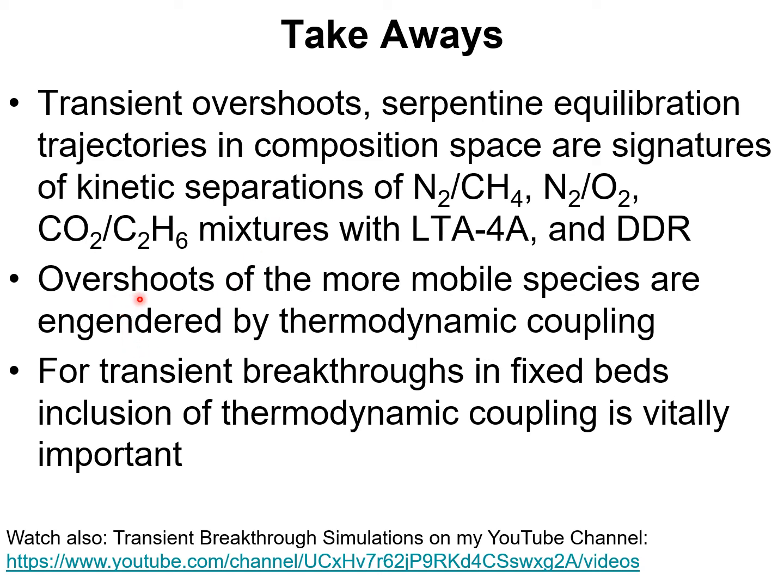The transient overshoot of the more mobile species is engendered by thermodynamic coupling effects that are described by a two-dimensional matrix of thermodynamic correction factors. For transient breakthroughs in fixed beds, we've also established that the inclusion of thermodynamic coupling is of vital importance in the determination of the productivity of the purified product exiting the fixed bed adsorber.